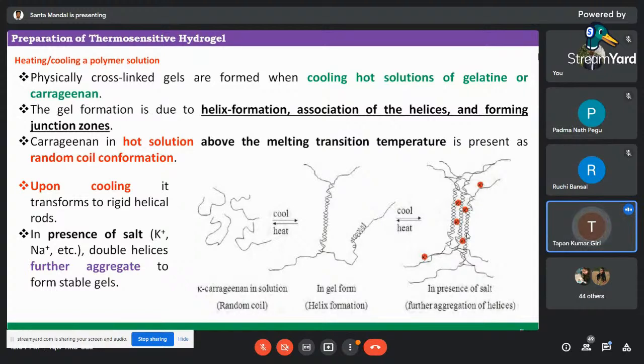When groups are coming too close to each other, converting from sol to gel. Carrageenan in hot solution above the melting transition temperature is present as a random coil conformation. Upon cooling, it transforms to rigid helical rods. In the presence of salt, K+, Na+, the double helix further aggregates to form gel.